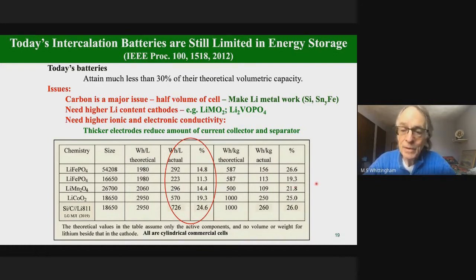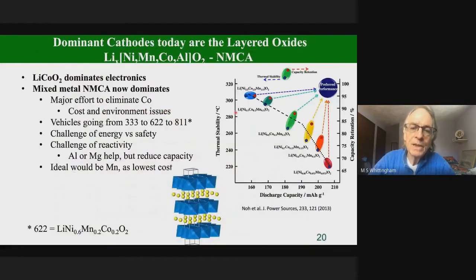And I'm part of a Battery 500 consortium whose goal is to get this number up to 500 watt-hours per kilogram. In other words, get our efficiency up to 50%. To do that, we've got to get rid of most of the carbon. As I said, it takes up half the volume. We need 72 grams of carbon to store 7 grams of lithium, so not very efficient. We need to use higher lithium content cathode materials. So the layered oxides, we only use about 60% of the lithium today. We need to get that up, and we need to use more than 1 lithium. The other thing is we need fundamental research to improve the physical properties of these materials. We have to make them better ionic and better electronic conductors. We could then use thicker electrodes and therefore reduce the amount of dead weight to things like current collectors and separators.